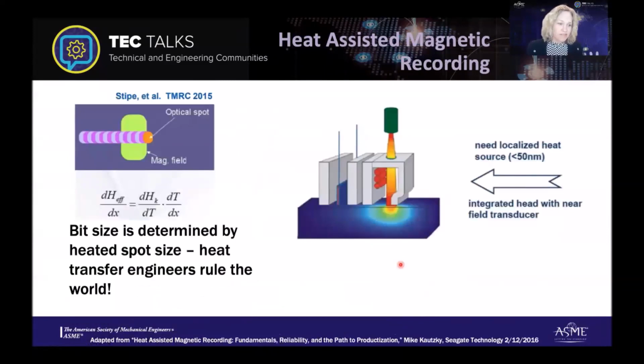And so this is actually one of my favorite parts of the story, because the bit's size can actually be determined by the heated spot. So you can have a larger magnetic write bubble, but you only write where the disk is hot. So that optical heated spot can determine the size of the bit. And so this puts us heat transfer engineers in charge of the write process, which is very exciting, but it also gives us some big responsibility here, because we need to figure out a localized heat source. And by localized, I'm talking about 50 nanometers, so an extremely, extremely small spot. And that spot needs to be immediately adjacent to where the writer is creating the magnetic field to be able to change the magnetization. And so this is now a pretty big challenge for us heat transfer engineers.